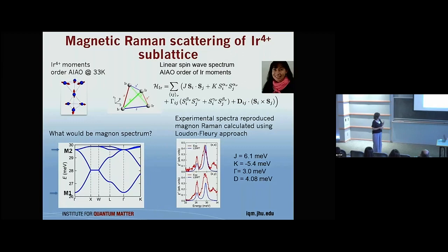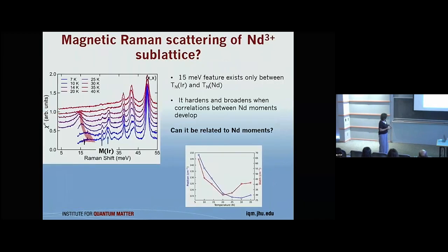So this is parallel, this is perpendicular polarization. And the intensities agree in a reasonable way. We have the high frequency band, which is a little high because the additional intensity comes from the fact that it's a degenerate band. So basically, the first step is done. From our spectra, we know where the one-magnon excitations of the iridium sublattice are, and we got these values for the interaction between iridiums.